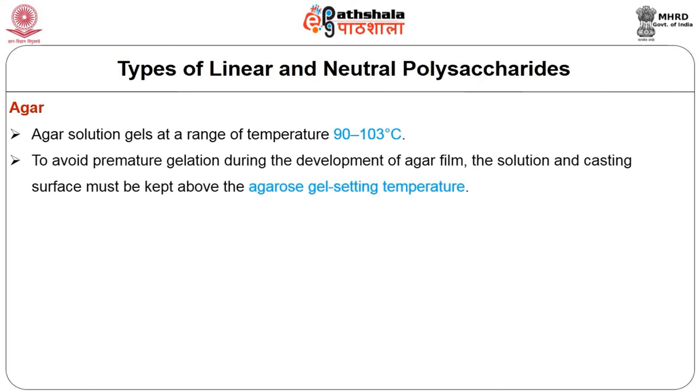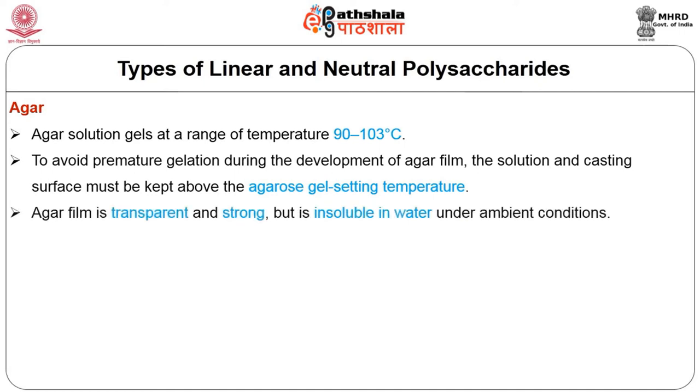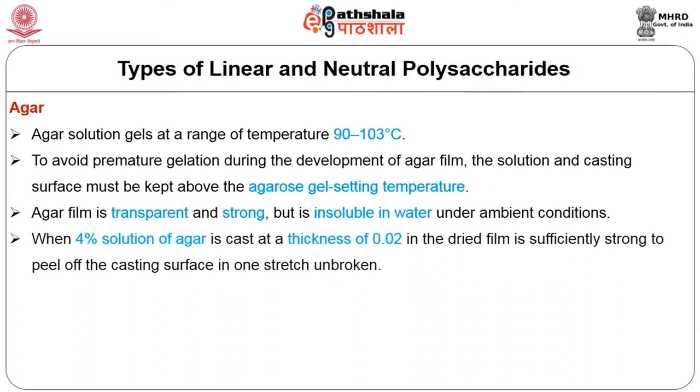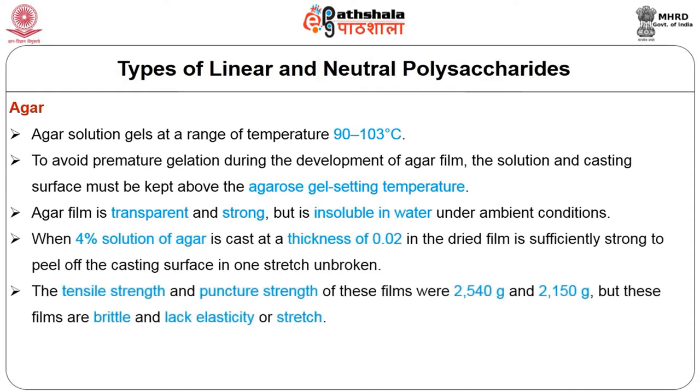To avoid premature gelation during the development of agar film, the solution and casting surface must be kept above the agarose gel setting temperature. Agar film is transparent and strong but is insoluble in water under ambient conditions. When a 4% solution of agar is cast at a thickness of 0.02 inches, the dried film is sufficiently strong to peel off the casting surface in one stretch unbroken. The tensile strength and puncture strength of these films were 2540 gram and 2150 gram, but these films are brittle and lack elasticity.